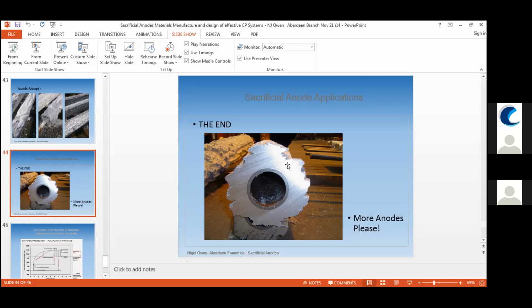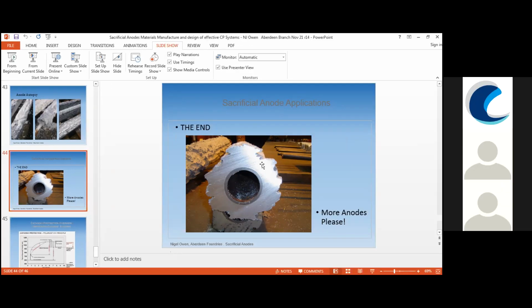Well, it's not something that's proportional, in a sense. The contamination of anode materials with iron and copper is probably gradual, but anode materials which have, say, iron of 0.15% usually need some other anode additions, as I mentioned earlier, to try and either mop up the iron by forming intermetallics, or to sequester the material, because iron goes into solution, and that's where it's actually causing some of the problems.